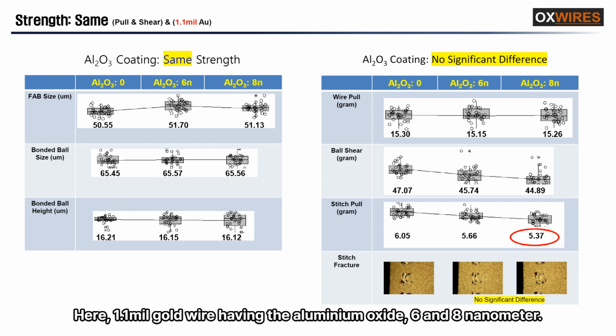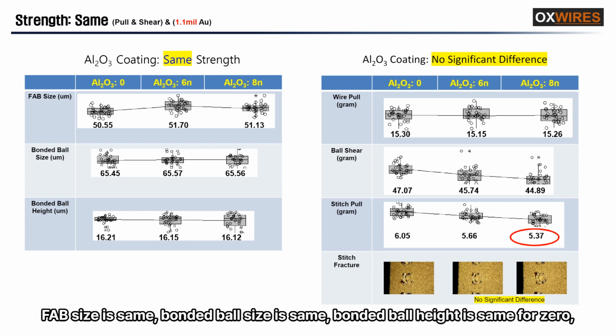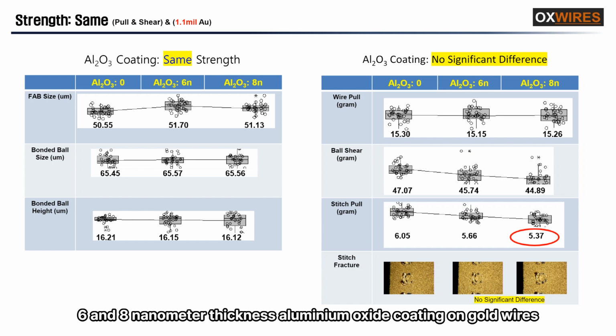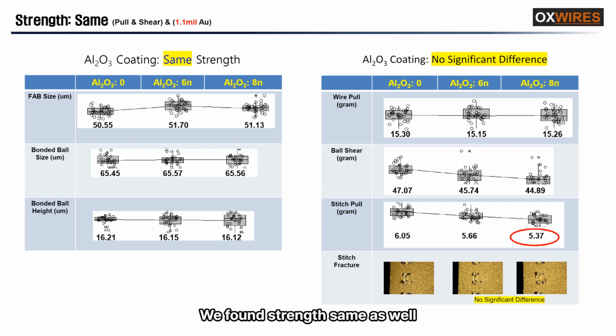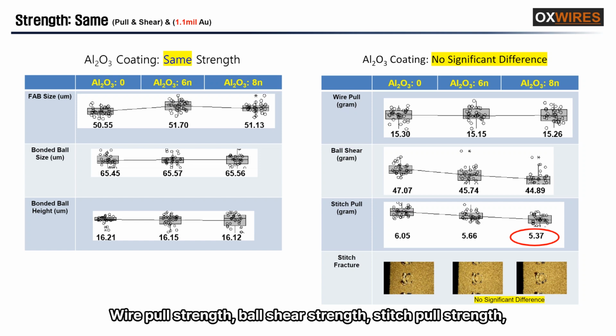Here, 1.1 mil gold wire having the aluminium oxide, 6 and 8 nanometer. FAB size is same. Bonded ball size is same. Bonded ball height is same for 6 and 8 nanometer thickness aluminium oxide coating on gold wires. We found strength same as well: wire pull strength, ball shear strength, stitch pull strength. There is a small drop, but stitch fracture is found same.